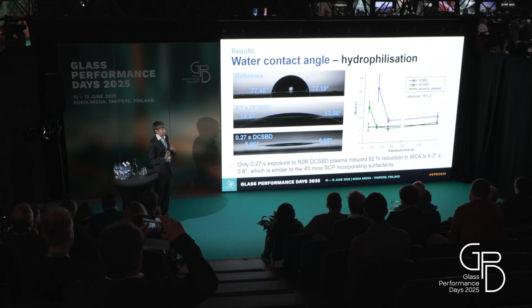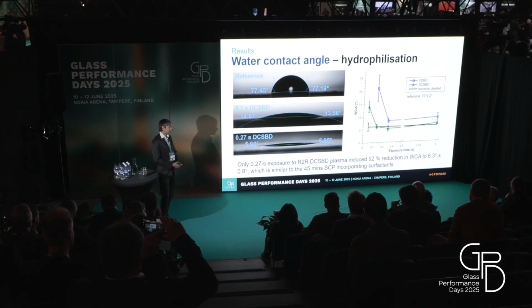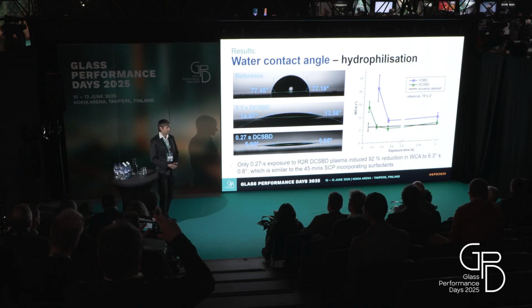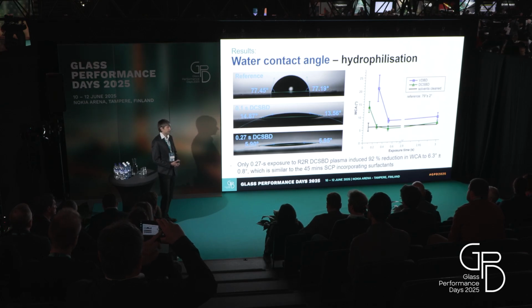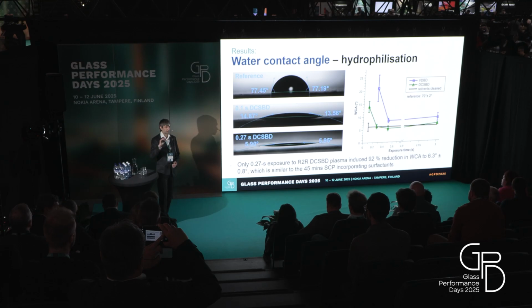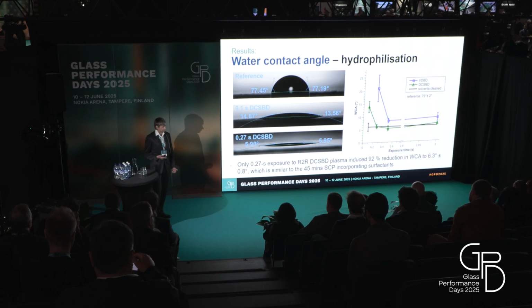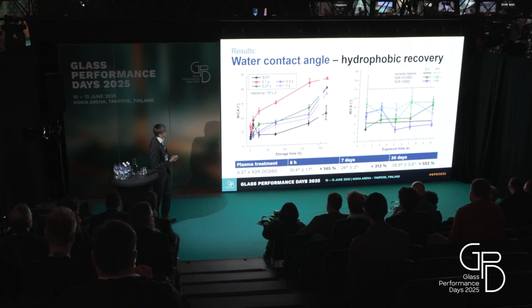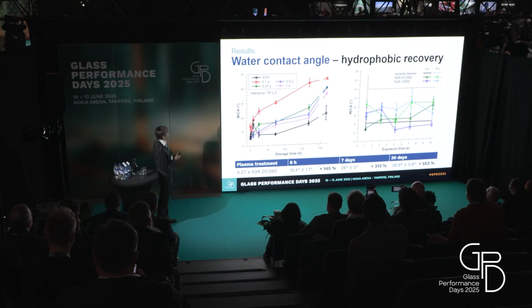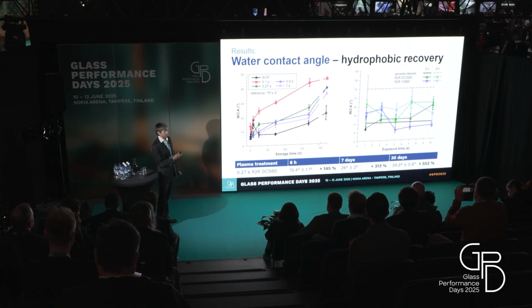And then what maybe is important if you are trying to involve plasma modification of surface in your technology is that you need to consider that the modification is done only in a nanolayer on the surface, and it's not so stable. So in different materials, we observe different recovery of this effect. So we then studied the aging. For flexible glass, when the reference was around 79 degrees, the aging even after 1 month doesn't lead to recovery to the initial value.